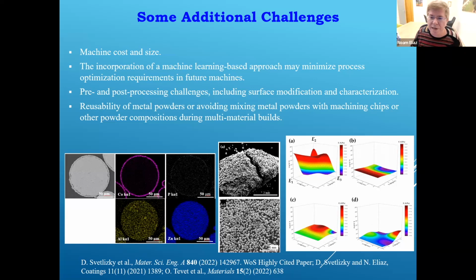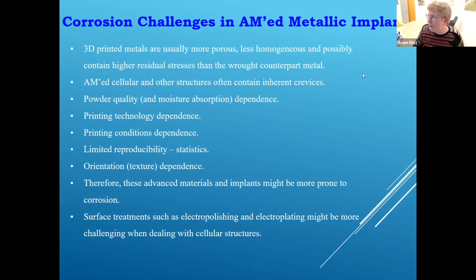So reusability of metal powders or recycling is an issue, in particular when you already worked in the printer with multi-materials. With respect to corrosion, and Ron is a worldwide expert in this area, there are some specific issues when you think about AM or additively manufactured materials with respect to corrosion behaviors. Typically they are more porous and less homogeneous and possibly contain high residual stresses than the wrought counterpart metals. If you were talking about cellular structures, you already have inherent crevices that could be the initiation sites for crevice corrosion. Powder quality, for instance, if you have moisture absorption, you might have hydrogen embrittlement, and so on. The corrosion behavior will be dependent on the printing technology because the microstructure, as Ron mentioned earlier, is important and will affect the properties.